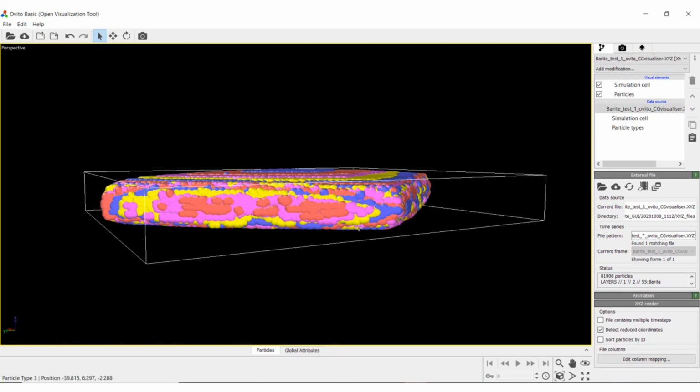So I hope this has shown you in detail how to use the layer coloring routine in Crystal Grower. It's essential to get your crystal coloring correct because it makes it a lot easier to spot features in the surface topology, which let you know if you've got your energies correct when you compare with in situ atomic force microscopy. And it also generally just makes your simulation images look a lot better. Once you've got it correct for a crystal structure and a certain crystal morphology, you can use this file with every simulation that gives you the same morphology, so you don't have to do this every single time.